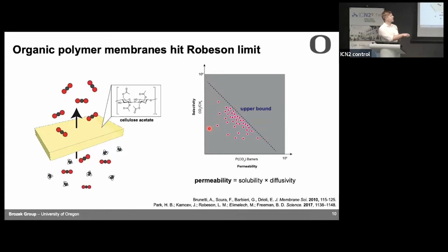If you plot the selectivity of a separation versus the permeability, that's basically how quickly the gas molecules are moving through, there's an intrinsic trade-off. The more selective a membrane is, the slower things are going to move through the membrane. This upper bound, which was discovered 10, 20 years ago, is called the Robeson upper bound. And people want to improve the performance of these membranes. One way to do that is by working with materials that have greater chemical tunability.